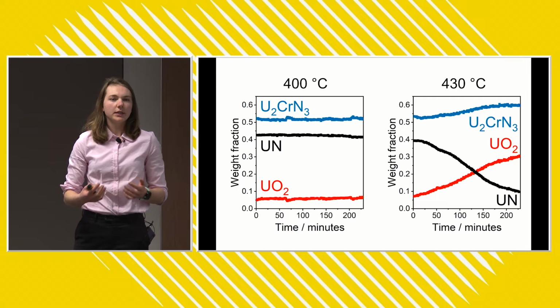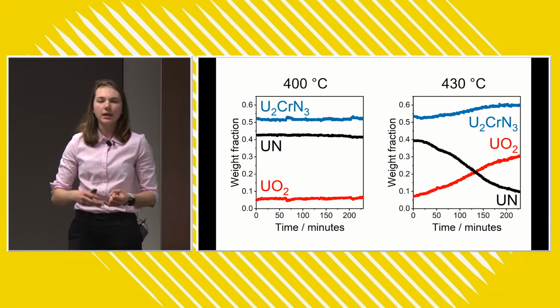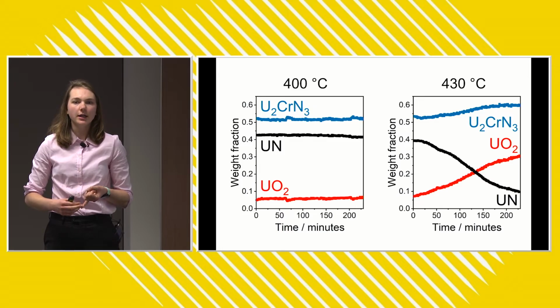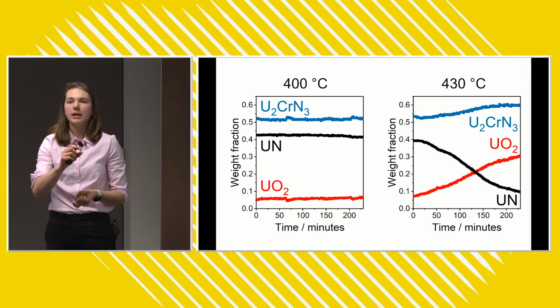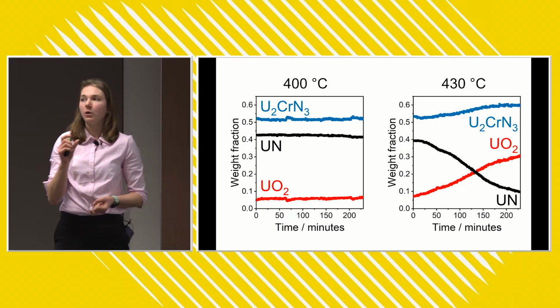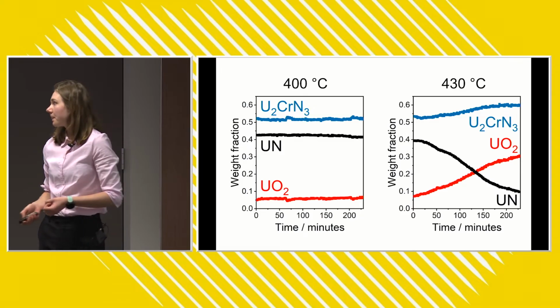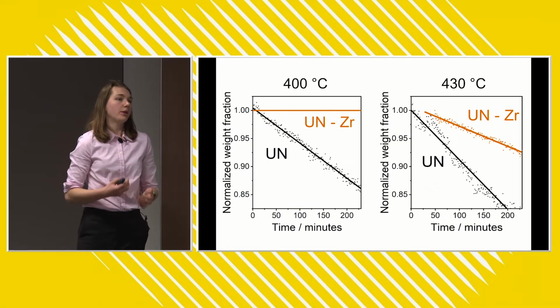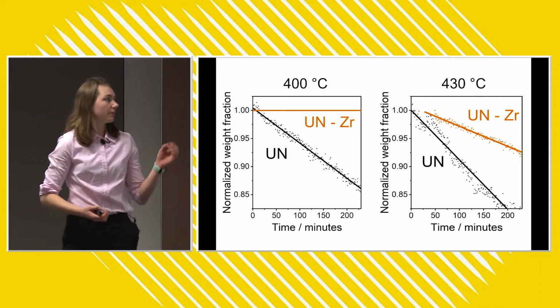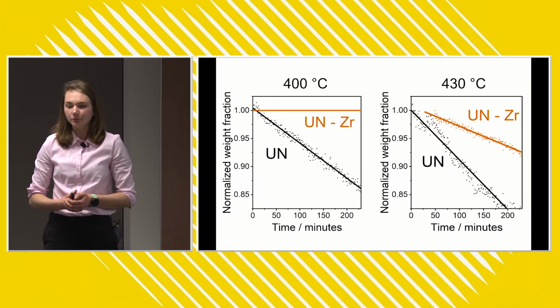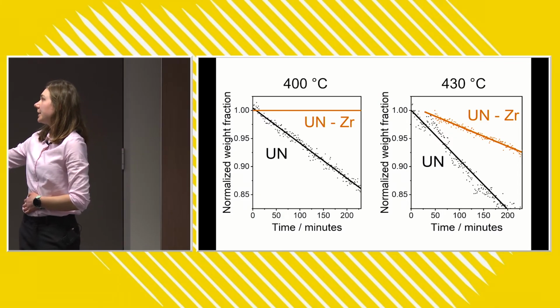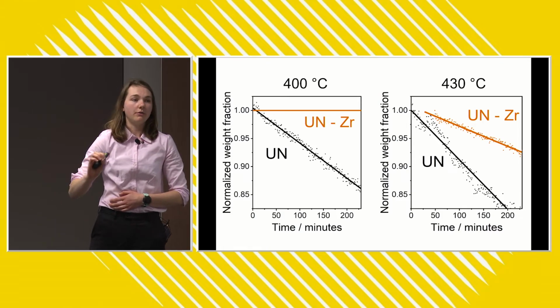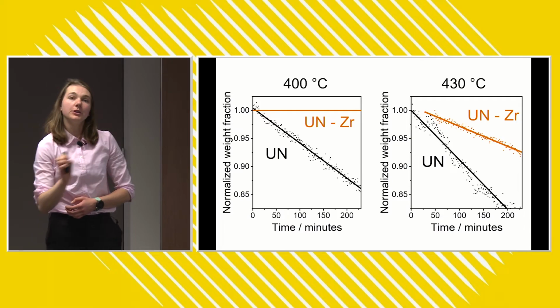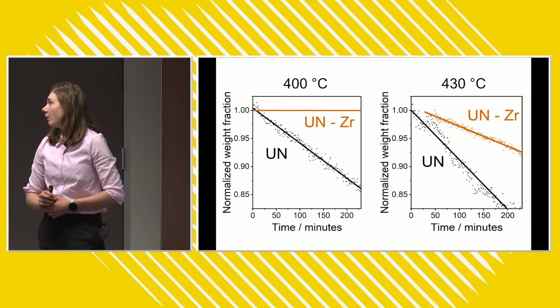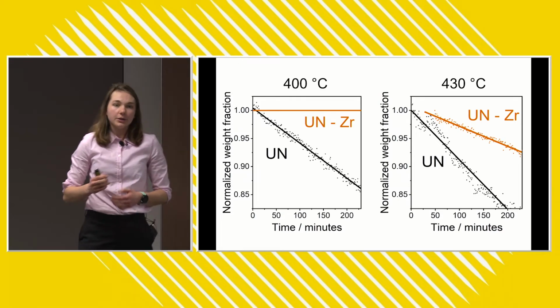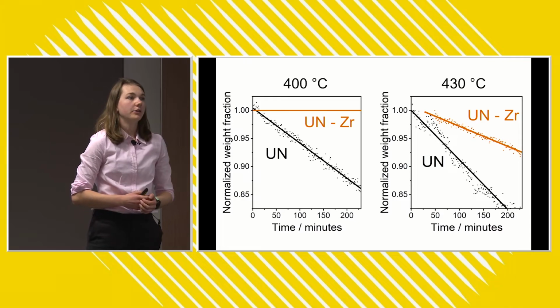So this led me to think of this hypothesis. Well, maybe the key then to improving the corrosion resistance of uranium nitride is finding an additive that is going to go directly into the uranium nitride matrix and just form a single phase fuel pellet. So we went away with our collaborators, tried a few things, and came across this zirconium sample. And this is amazing. You can see in the data at 400 degrees C, we're not even getting any oxidation of that uranium nitride fuel pellet with the zirconium additive. And even at the higher temperature of 430 degrees, there's a little bit of corrosion happening, but it's at a much slower rate than the uranium nitride.